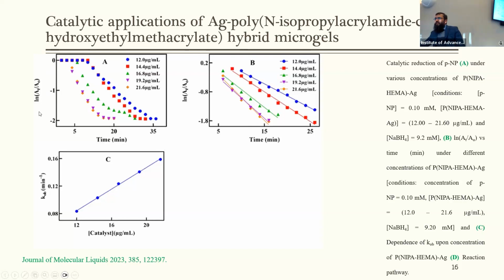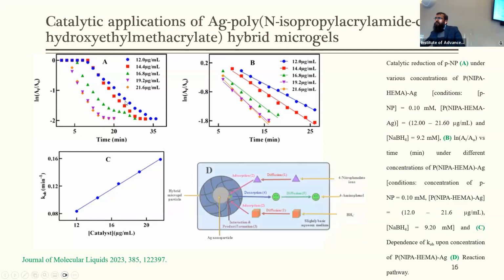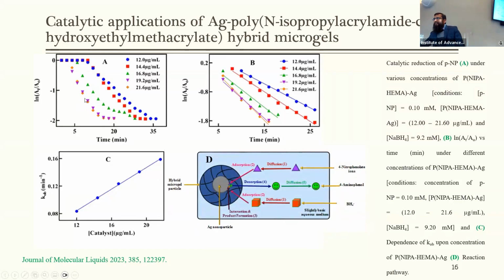The time in which log of At over A naught does not change with time is called the induction period, and it is a well-known property of catalytic reduction of p-nitrophenol using polymer stabilized metal nanoparticles. We use the region from after the induction period to the completion of the reaction to measure the rate constant from the slope of the plot. So we use this plot for the determination of the rate constant for reduction of 4-nitrophenol.